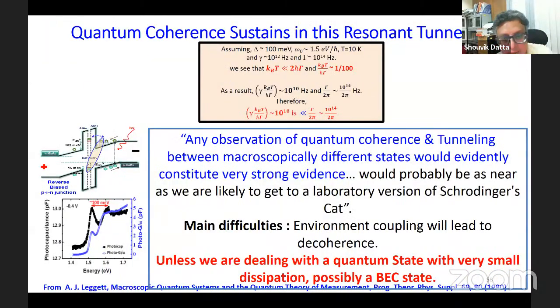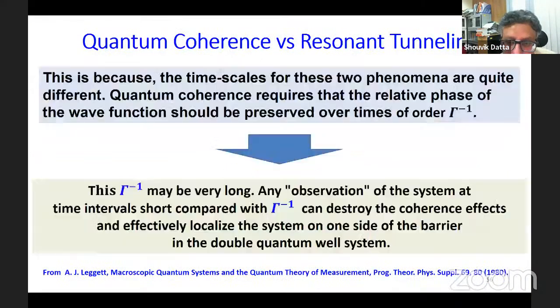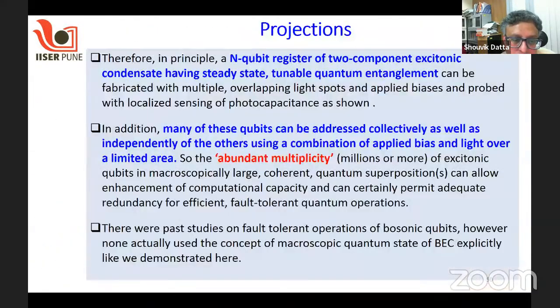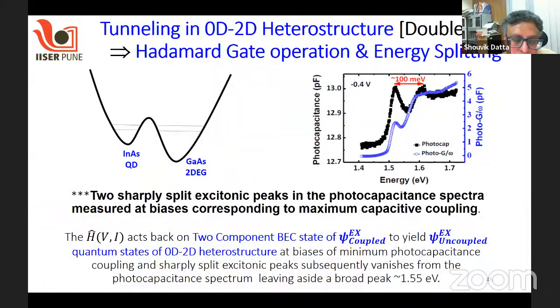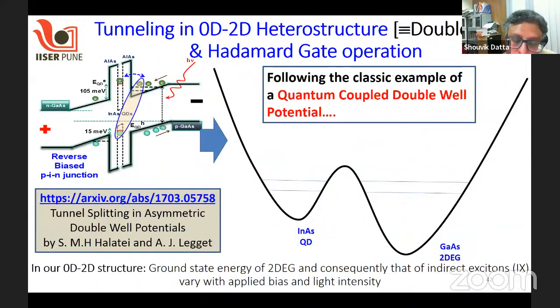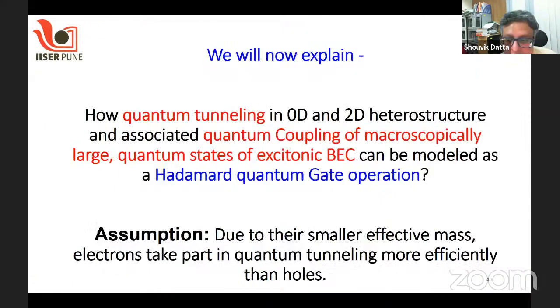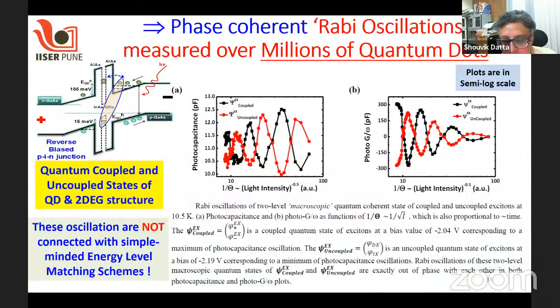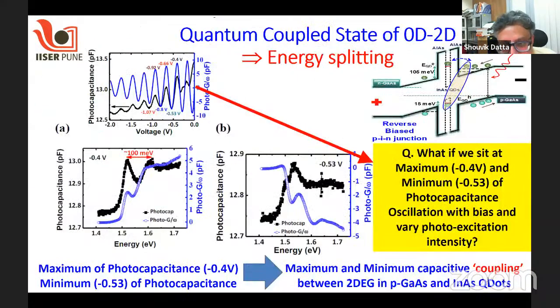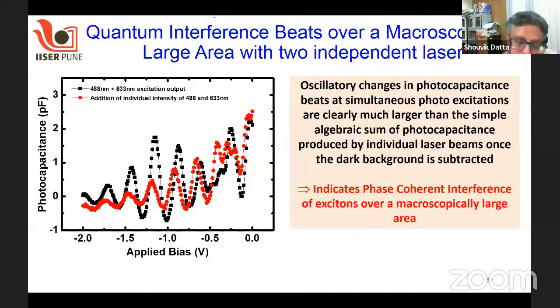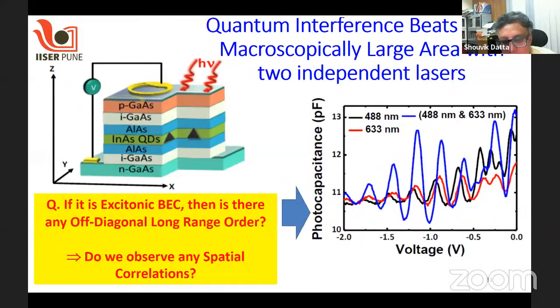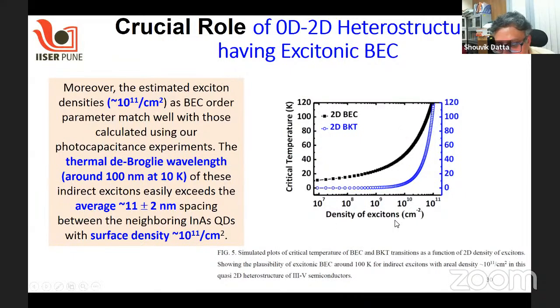I mean, that's definitely happening, that that is increasing, but we have also calculated the de Broglie wavelength, and it is much larger. Even at those temperatures of 100 Kelvin, you can see the de Broglie wavelength is much larger than the spacing between the excitons. So as a result, it shows that the Bose-Einstein condensation should take place. Why it should not take place when the de Broglie wavelength around that temperature is pretty large compared to those indirect excitons, which are anchored with those quantum dots.